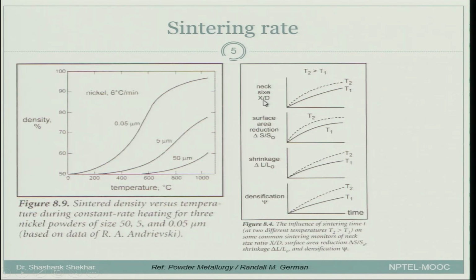So, here is the neck size x over d. You remember x is the size of the neck; x equal to 0 means the particles are just in point contact. D is the diameter, and on the x axis you have the time. For two different temperatures, it is shown how x over d is changing. For lower temperature you get lower x by d, for higher temperature you get higher x by d. That is one thing. But what you see is that in the initial time period, the rate of change of x by d is large, and with time it gets saturated. So, again our concept that this rate is higher at initial stages still holds true.